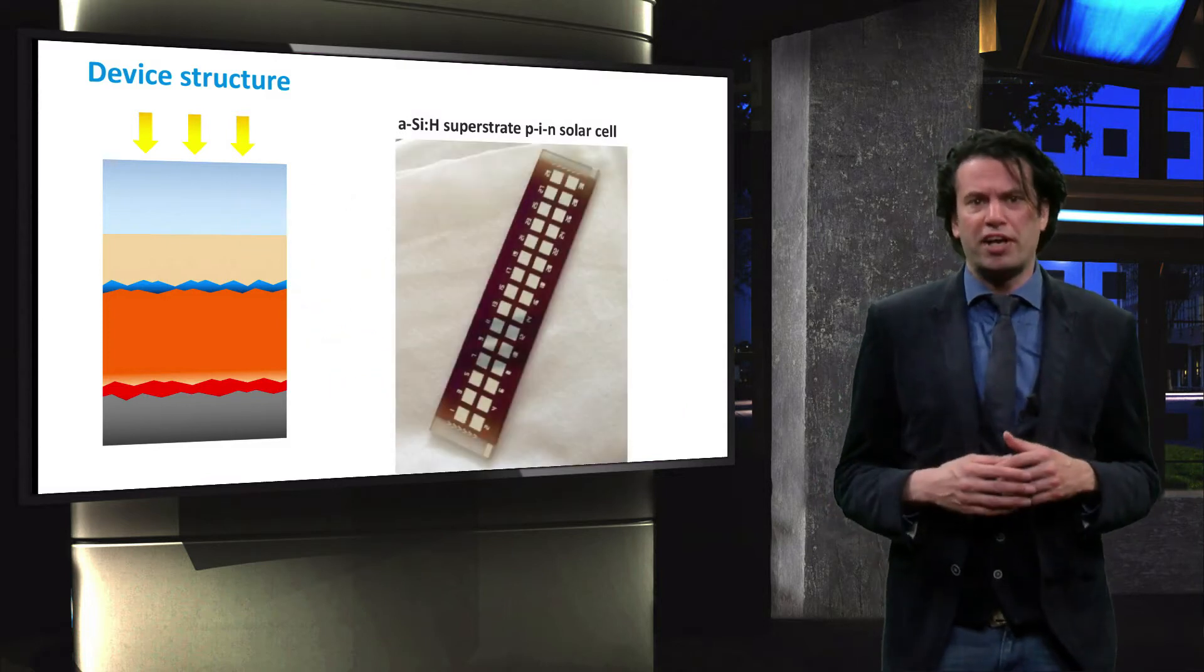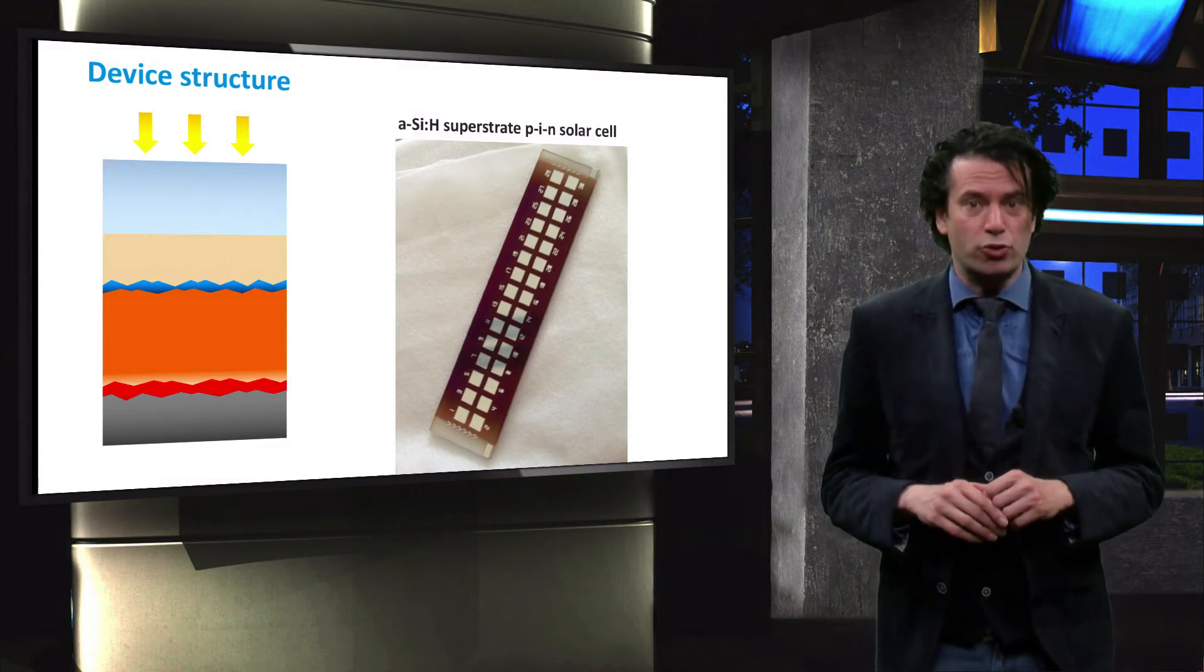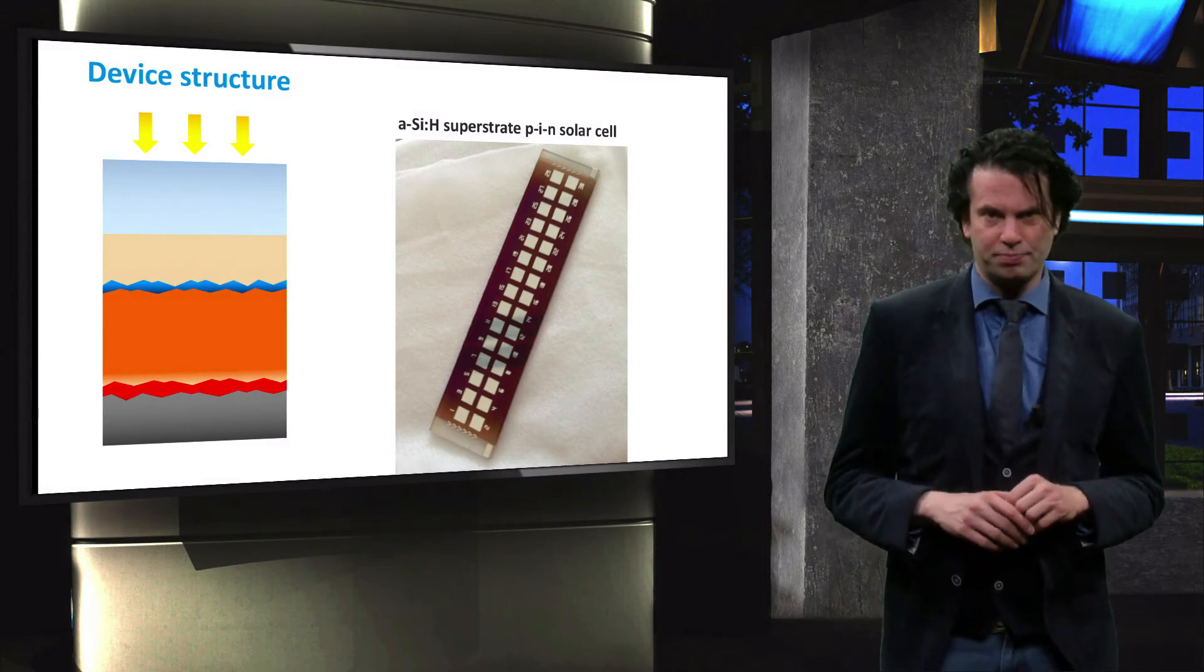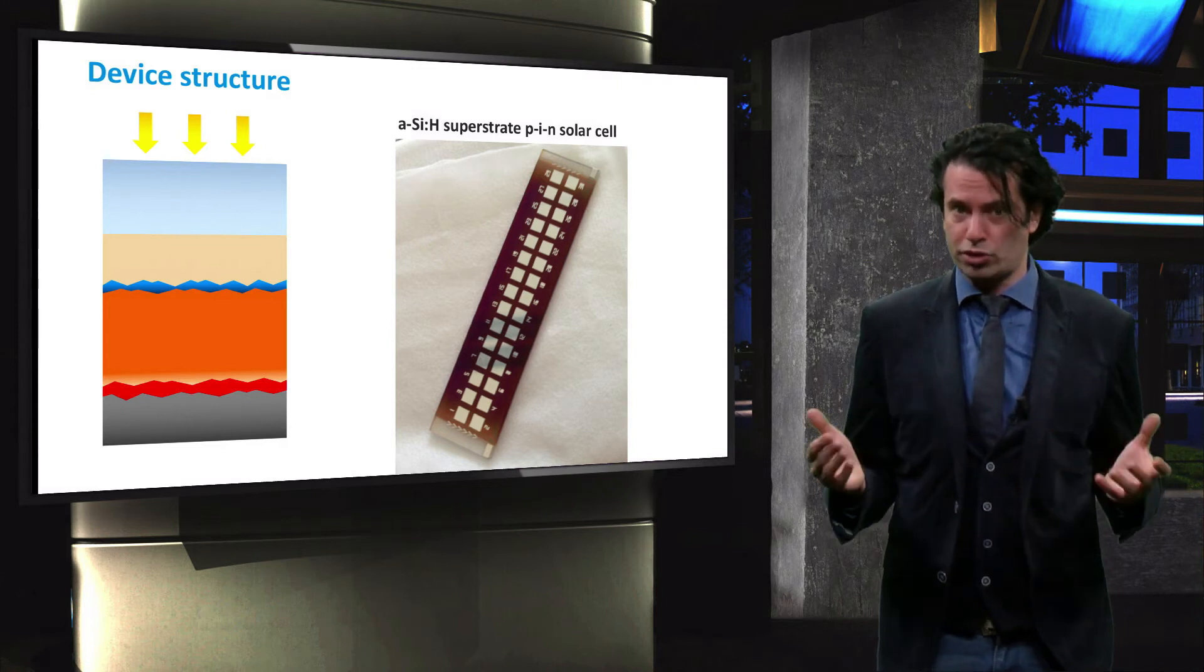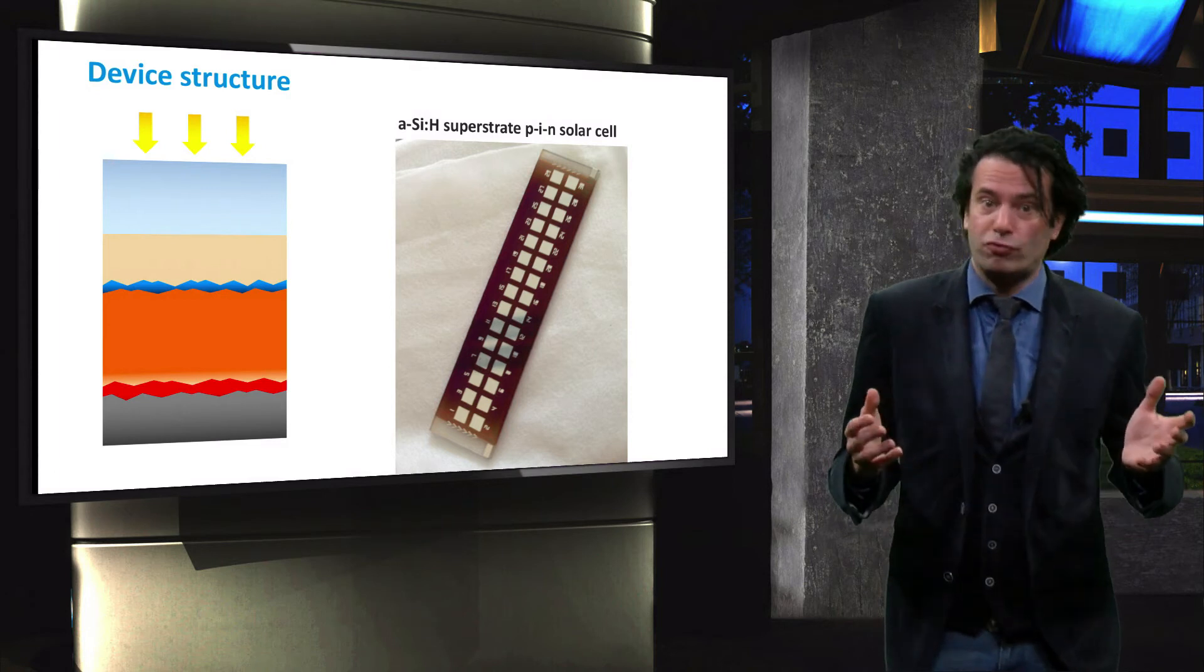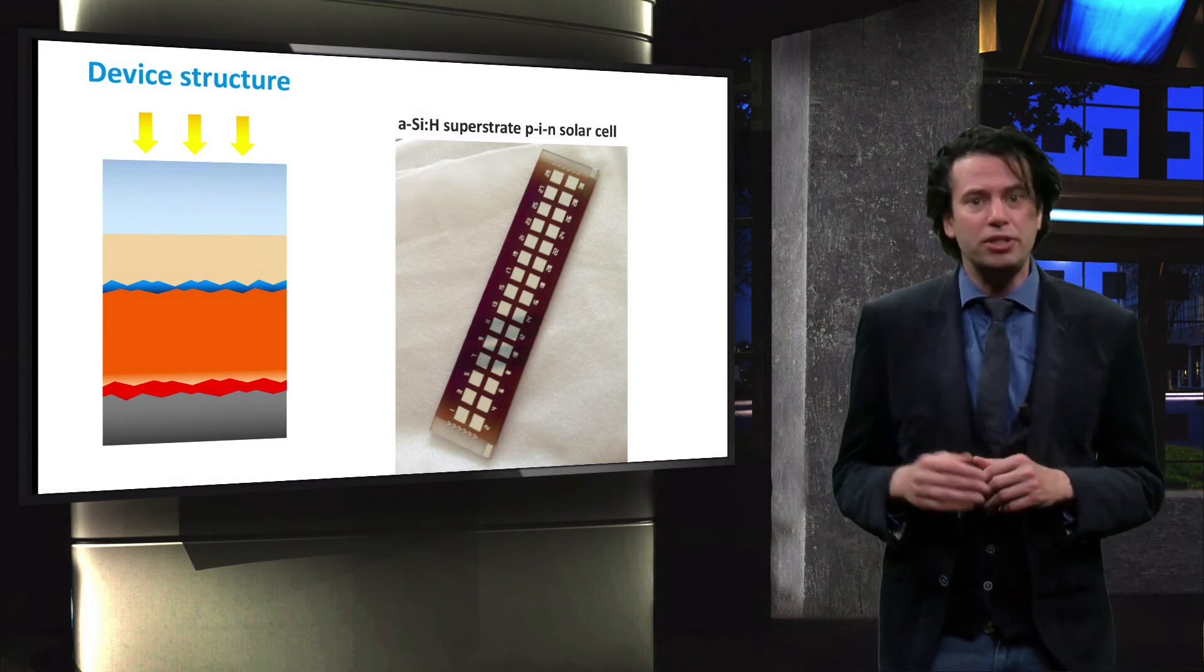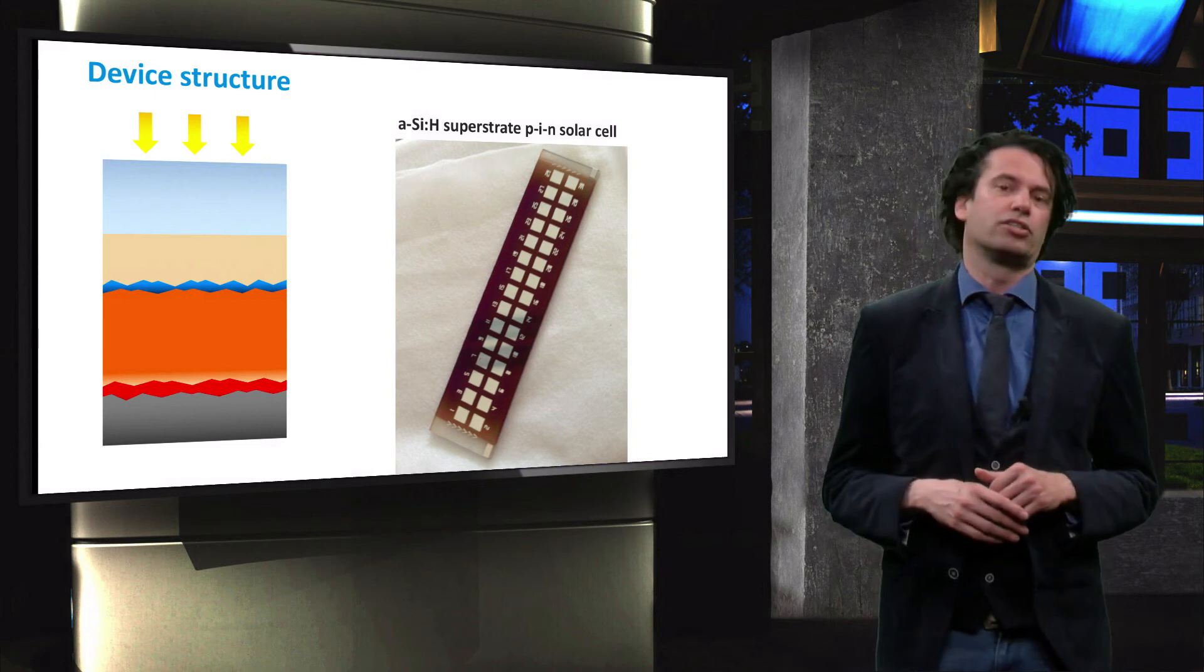On a small glass substrate, 30 separate tiny solar cells are defined by a metal contact of about 16 square millimeters or 8 cells of about 1 square centimeter. If you want to process multi-junction thin film silicon solar cells, an additional PIN structure based on for example hydrogenated amorphous silicon-germanium alloys and hydrogenated nanocrystalline silicon alloys will be deposited after finishing the N layer of the amorphous silicon cell.